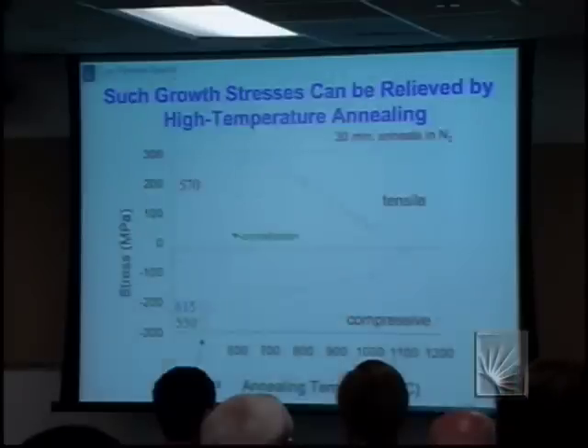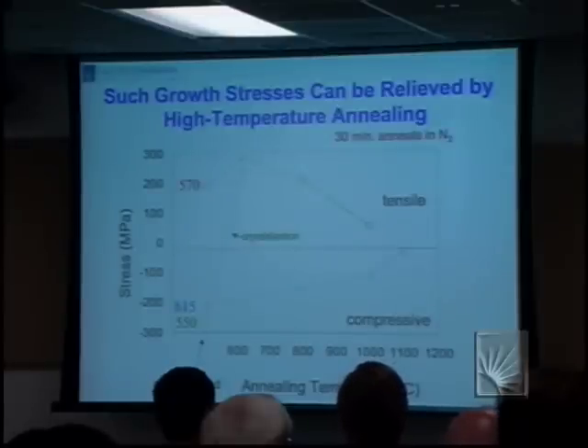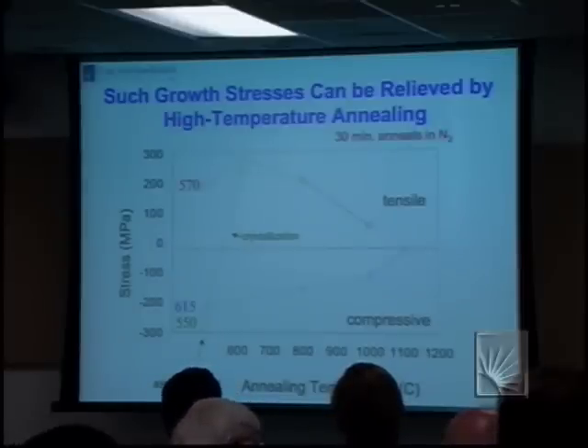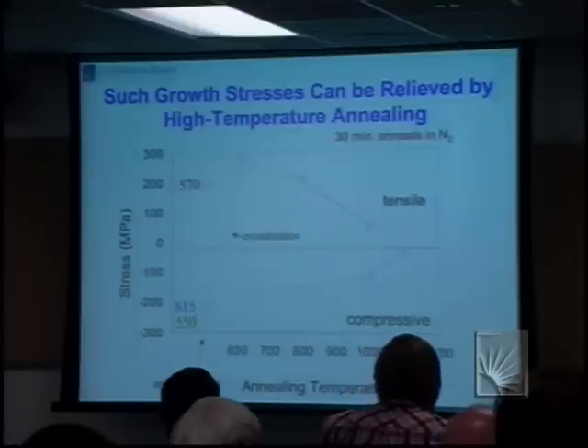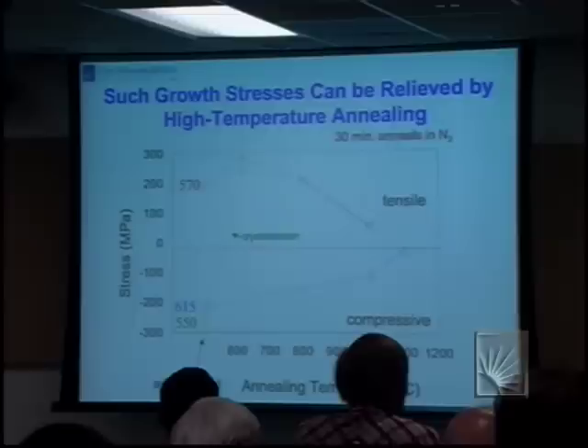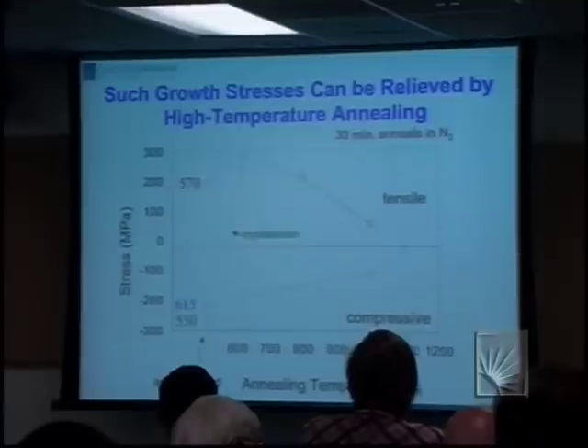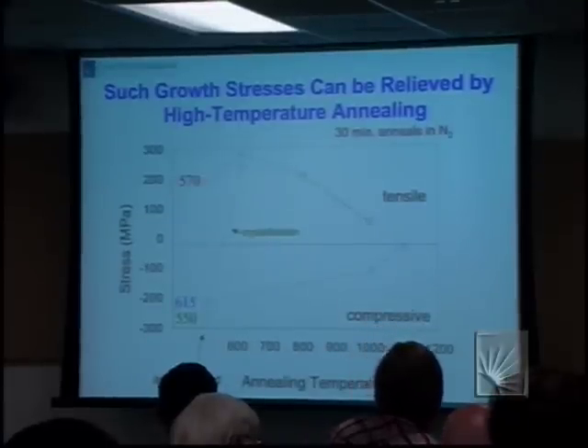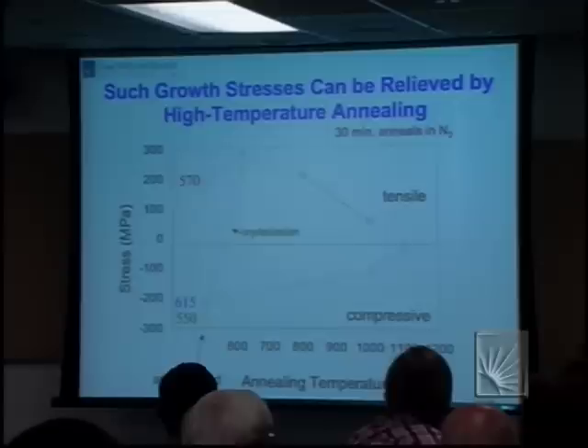Okay, these stresses can be relieved by high temperature annealing. And so this is the magnitude of a 550 and 615 deposit and the 570 deposit. And then if you anneal these, let's talk about 570 first. Tensile stresses first increase if you anneal at 570. This increase is due to that last bit of uncrystallized material, the last 20% crystallizing by this post-deposition heat treatment. And then you begin to get some annealing. Likewise, 615 is compressive, and as you heat up, you get some annealing.